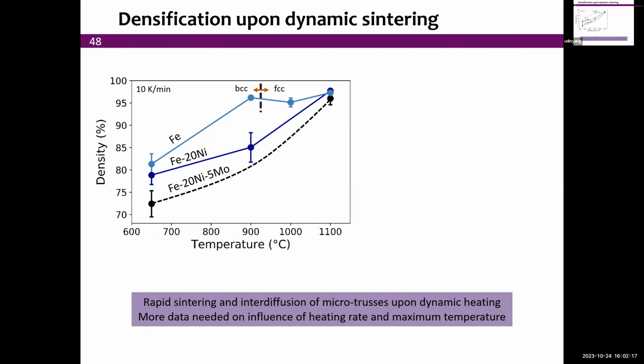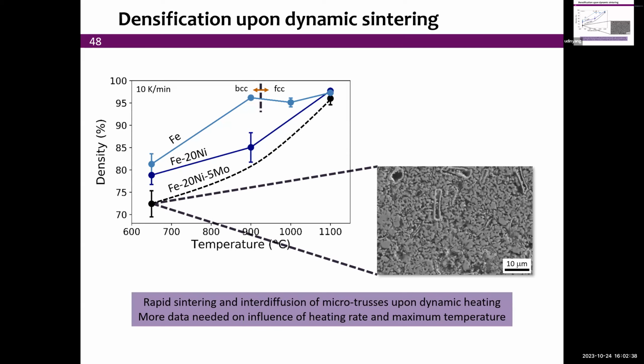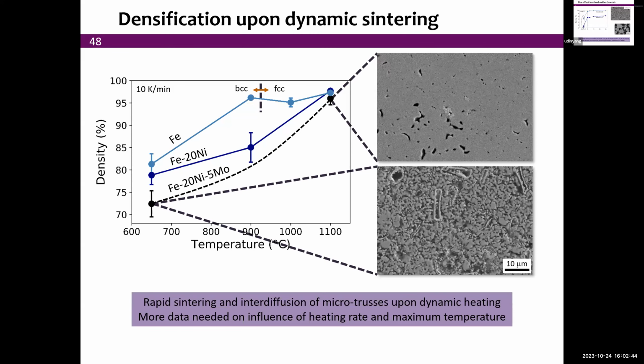Now, again, looking at density as a function of temperature, we see that the iron, with that caveat from BCC to FCC, really sinters relatively quickly to about 95%. And as we alloy, it becomes more and more difficult to sinter. And that's because also we have slower diffusing, especially the molybdenum is slower diffusion. And so we need to kind of look at the microstructure. This is relatively unsintered, as shown here.